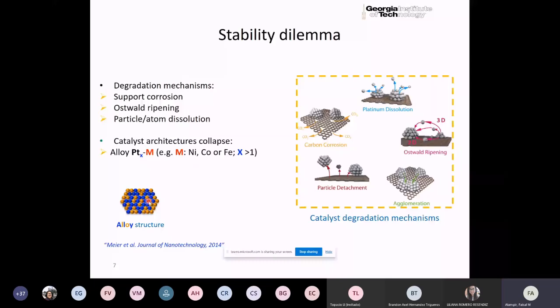Or you could try to put the platinum, for example, just as an exclusive surface layer, but even then you could over time hollow out the particle, because the element that's more reactive on the inside can over time leach out. Not more reactive for the catalytic reaction that you're interested in, but more reactive from a corrosion reaction point of view. Anyway, all of this got us thinking, why should we try to make things three-dimensional? Three-dimensional particles, these nanoparticles, have a lot of inherent problems. First of all, you don't know what you have. You have things that are described as an average, right?